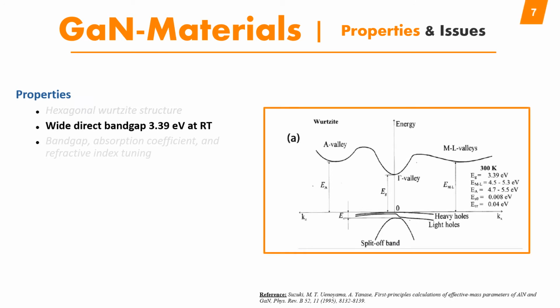Optically, these materials have a wide and direct band gap of 3.39 electron volts, which is wide, in the UV region, and this band gap can be tuned by changing the metal concentration in the alloy. Before we go through this, we can see from this figure the calculated band structure for gallium nitride. We see that the valence band maximum and the conduction band minimum are on top of each other in the k vector, so this is a direct band gap material.